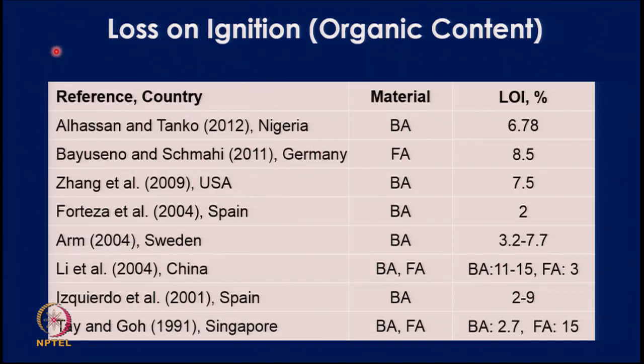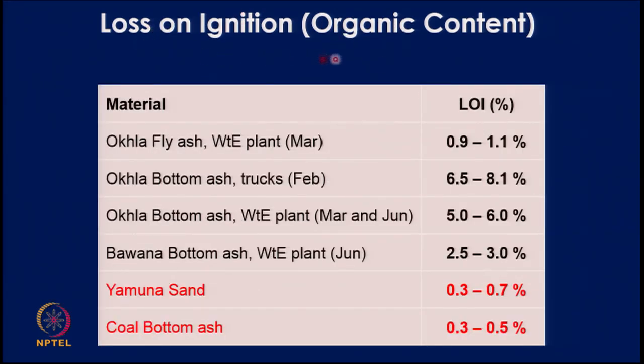If you look at the data reported in literature on loss of ignition in the muffle furnace, then in the incinerated ash, the LOI can be as low as 2%, but it can be as high as 15%. That means all the organics are not completely burnt in the incineration process. Some values are now coming in from the two waste to energy plants in Delhi, and what we observe is that the LOI can be as low as 0.9%, but can be as high as 8.1%. This also seems to be dependent on the weather conditions during the cold winter months, like in February, burning of the organics may not be as efficient, whereas in the summer months, say June, the burning of the organics may be more efficient.